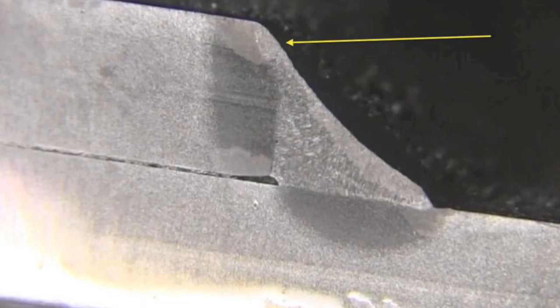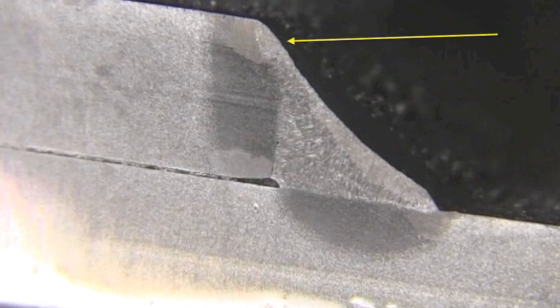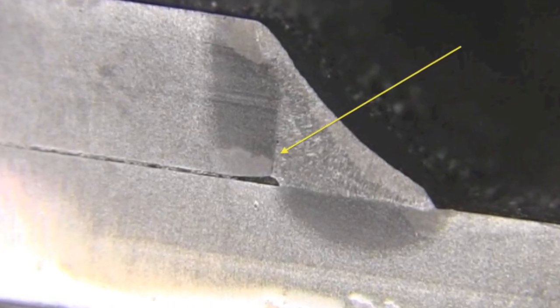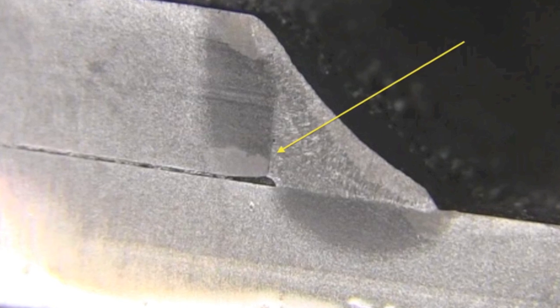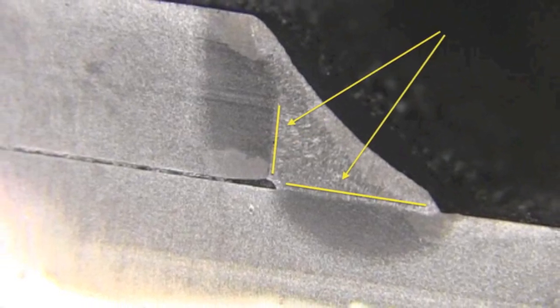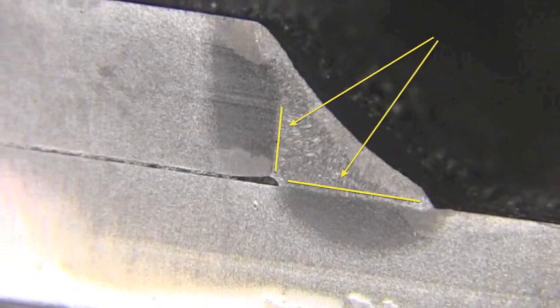Let's look at that arc again now. This is right about where we cut it. And then let's look at the cross section. Up there in the top, it did a pretty good job of melting that corner, but down there near the root of the joint, you actually have a real straight line here. A straight line is the last thing you want to see when you're testing a fillet weld like this.